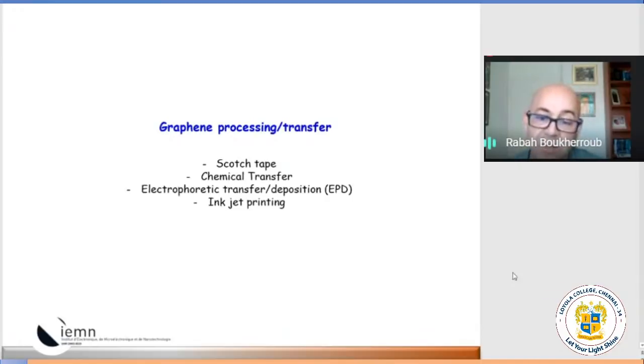But also, if you deal with the material you buy or you make, which is called chemically derived graphene, then you also want to transfer it. You can have just a droplet, because you can have it in a solvent or in water if it's water dispersible. But there you don't control the number of layers. So you let the water evaporate, and then you have the restacking of the graphene sheets, and that can potentially lead to losing the characteristics of the graphene, okay? So you have to find really different ways of transferring that.